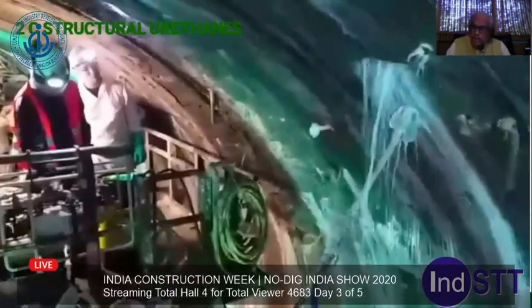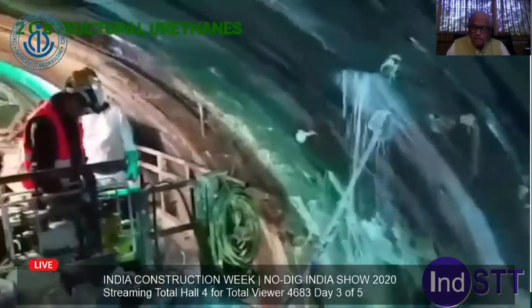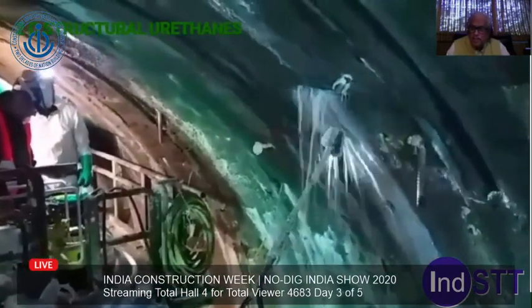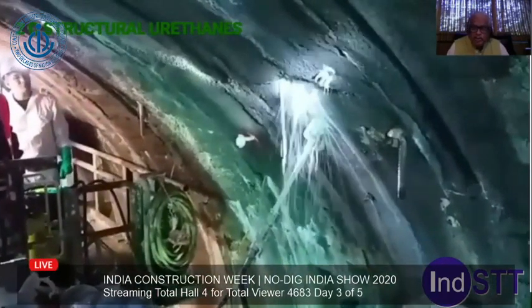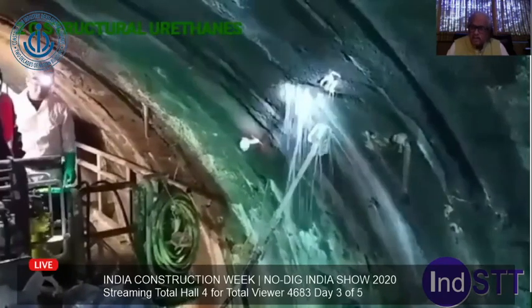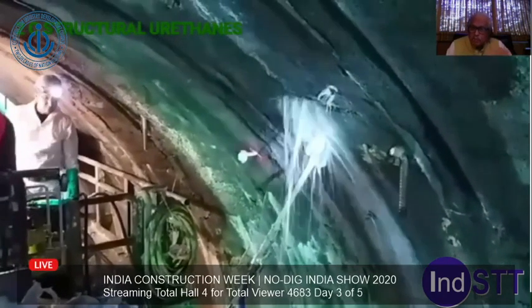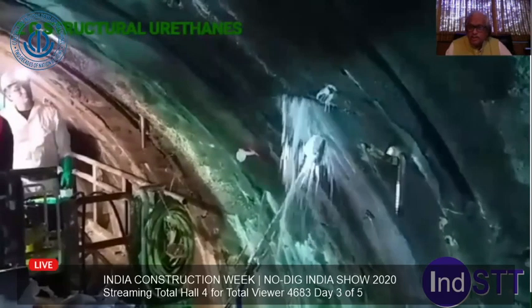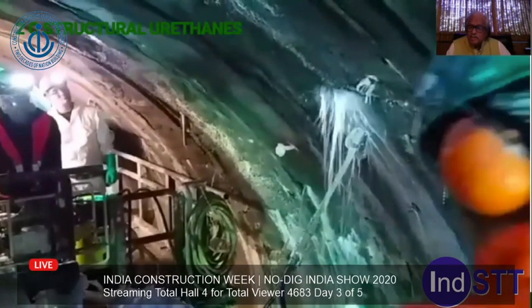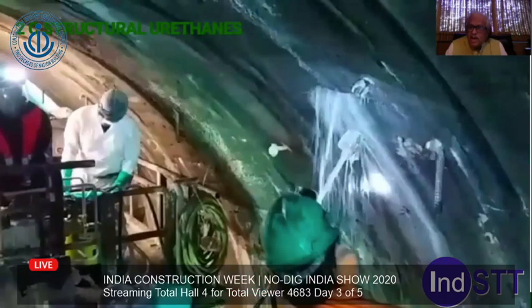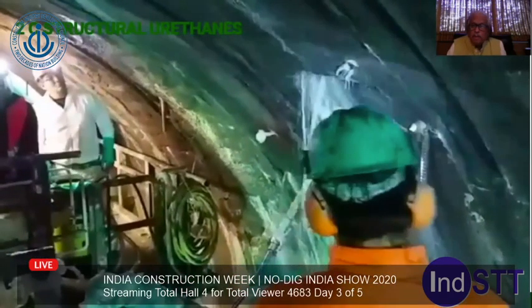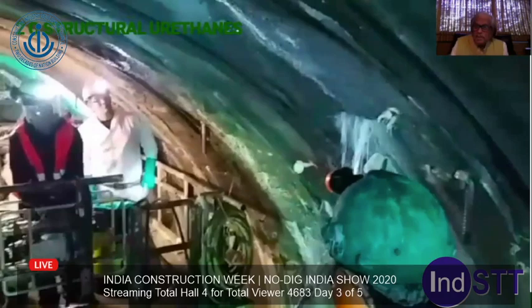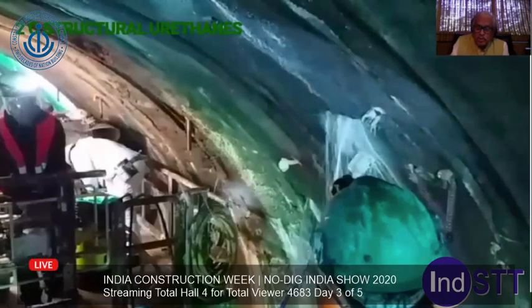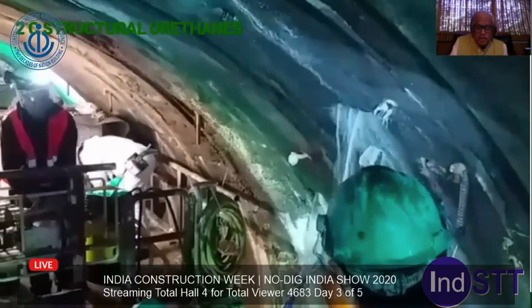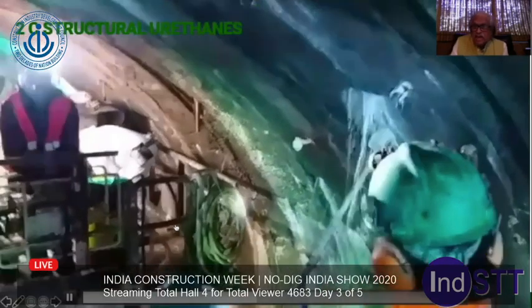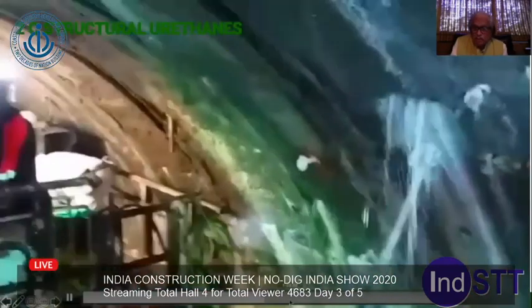Because to stop this type of water coming under such a pressure of 6 bars or 10 bars, you really need polyurethanes which are structural, which can harden totally underwater within a period of 1 to 2 minutes. So totally your construction can go unabated, as well as it forms a permanent seal. It's a permanent solution. If you see, the water is going on reducing in a matter of just minutes. So this is the real live stopping of water.